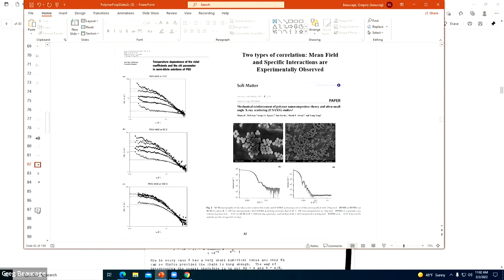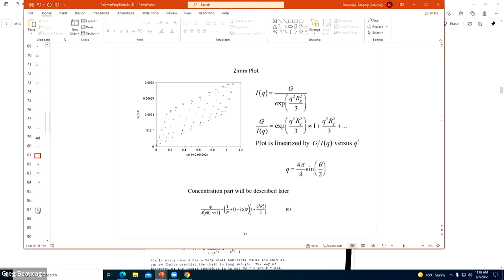So see if I can find this here. This is kind of what that prefactor is from the osmotic. So you have 1 over I, because basically that's direct. 1 over I is directly related to osmotic compressibility. It kind of makes it easier. So it's going to be the derivative of the free energy with respect to composition. That will give you this expression.